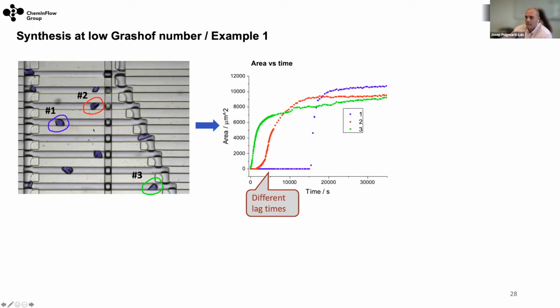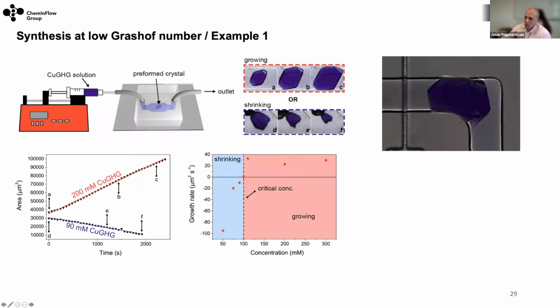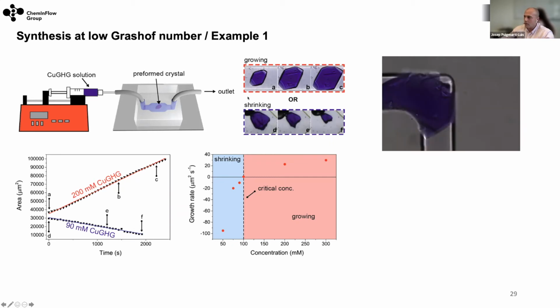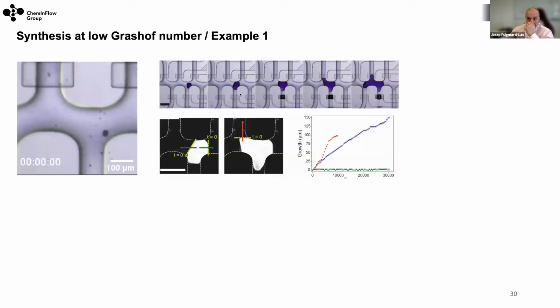So we have a lag time, and all the crystals grow at different times. But what we observe is that there is a critical concentration, and this is 100 millimolar. Above this concentration, we can have a constant growth of the crystal. So if we add the solution, this MOF crystal will continue growing. If we are below, then we can dissolve it. So this is the ideal condition to try to shape the crystal.